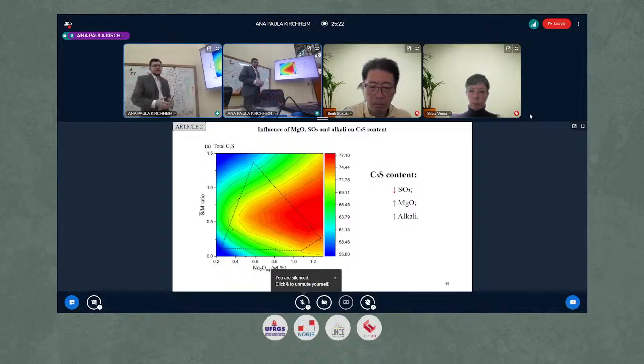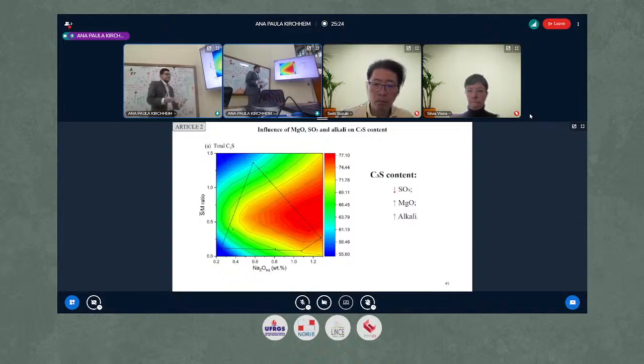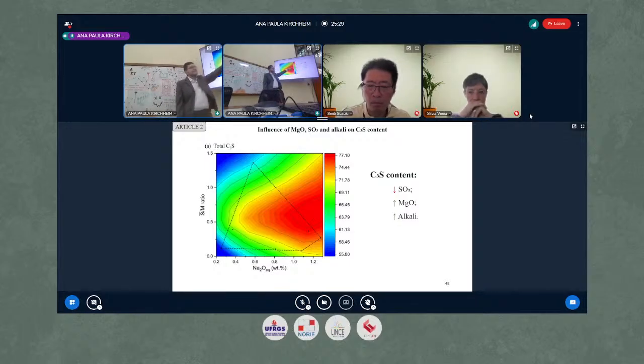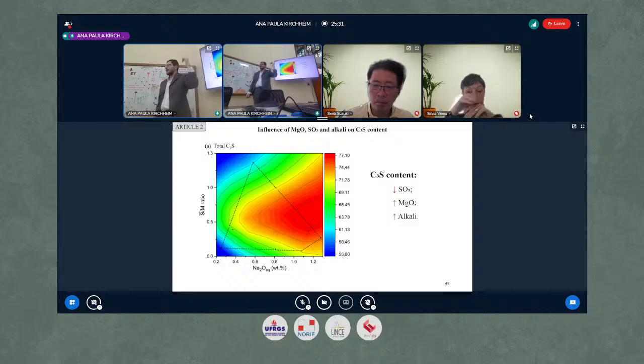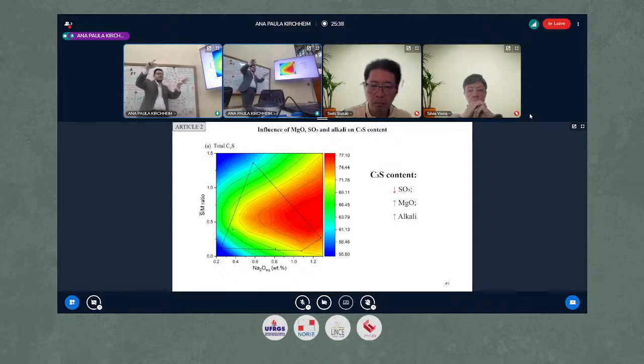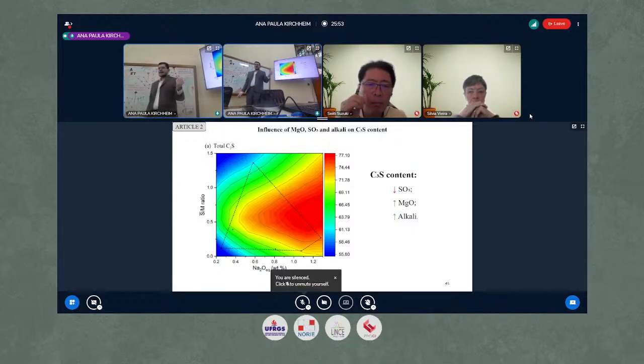So also talking about the results, we see here a great correlation of alite with sulfate and magnesium, again as observed in the first study. The higher the sulfate, the lower the alite content and the higher the belite content, while magnesium stabilized alite instead of belite. Again, in agreement with the first study. But here we also find a significant effect of alkali. The greater the alkali, the more alite is formed.